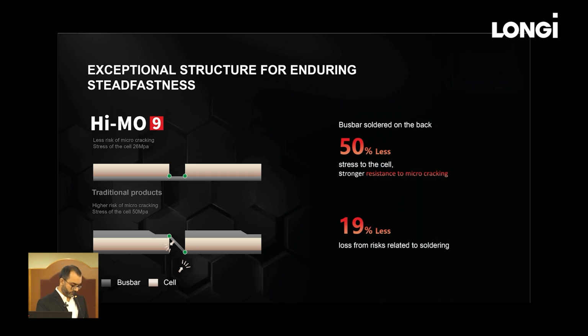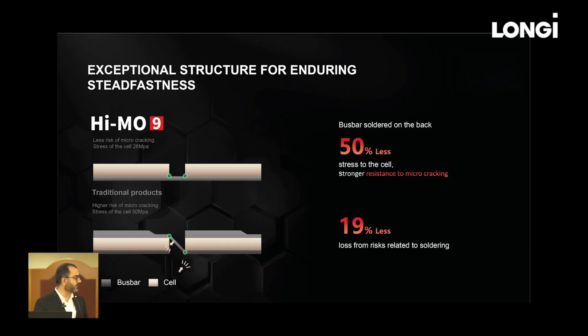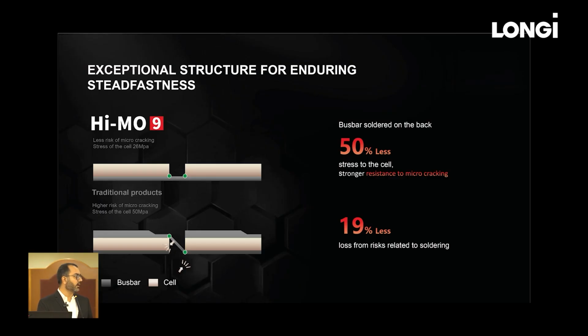Yes, so with Hi-MO 9, we are going with the I-type welding. Traditionally, the modules have Z-type welding. What happens in the Z-type welding is the pressure around the edges of each cell is around 50 megapascal. But with Hi-MO 9, it's around 26 megapascal, so 50% has been reduced. And again, due to the soldering, a 19% reduction in soldering-related risk has been achieved.